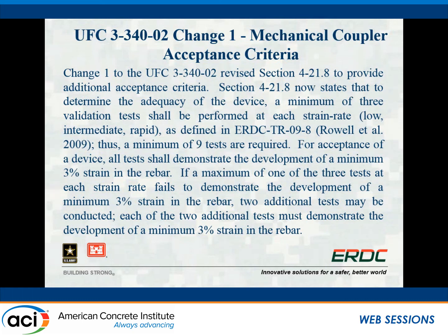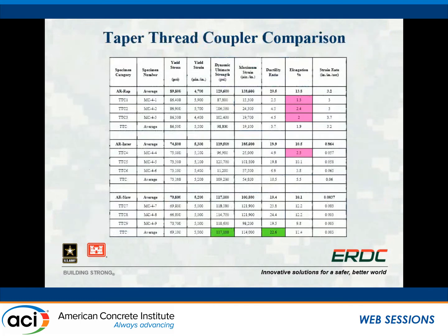And so if out of those triplicate tests, all of them have similar tensile strengths and they exceed 3% elongation, you can accept those couplers for use. Now, if 1 out of the 3 actually doesn't meet that 3% strain, we can test 2 additional samples. Those 2 additional samples have to meet the 3% elongation requirement, so a total of 4 out of 5 have to meet the elongation requirement. Otherwise, that coupler is rejected.